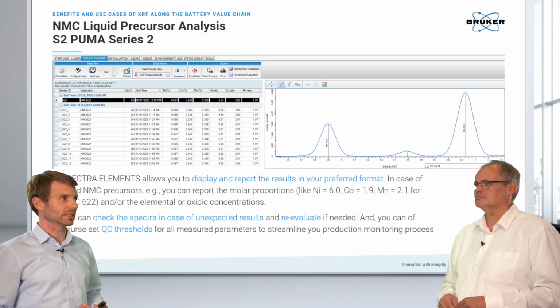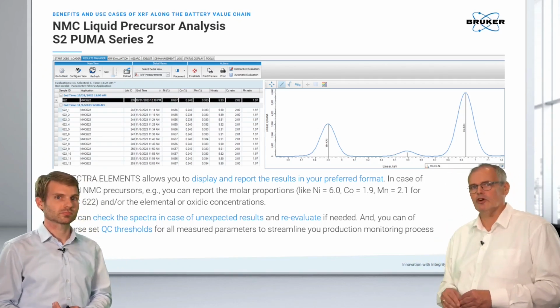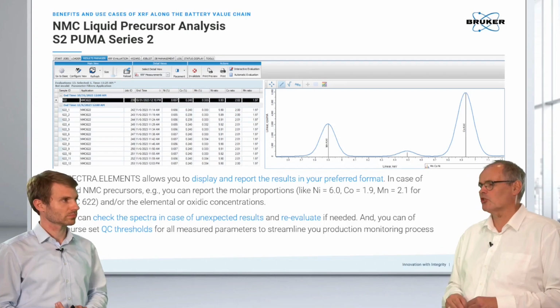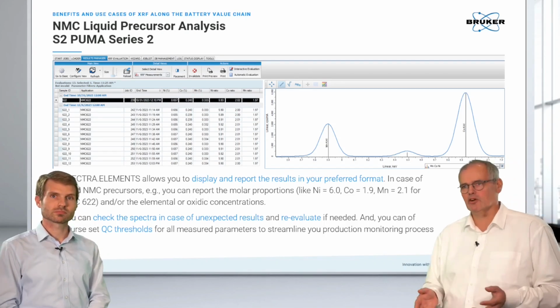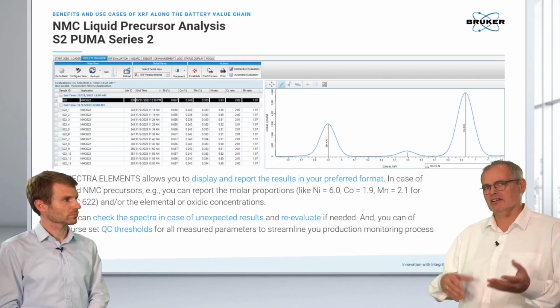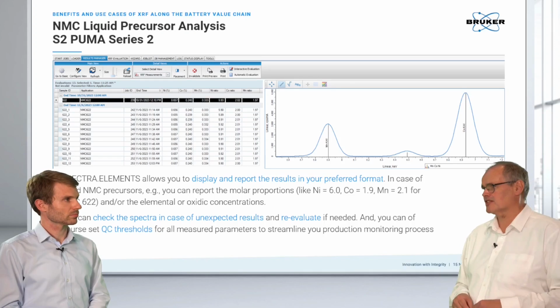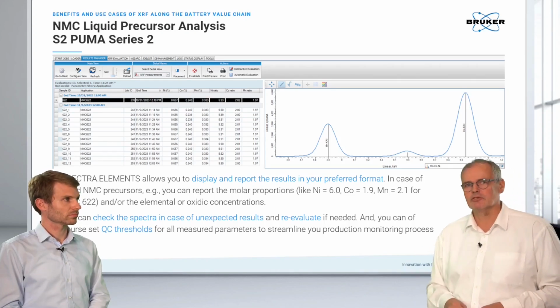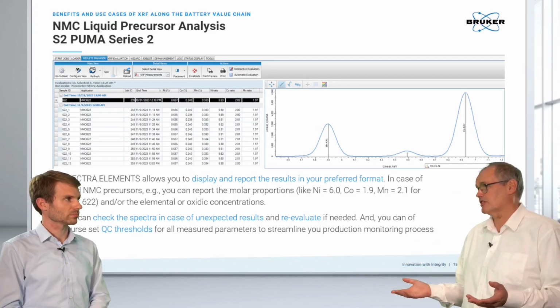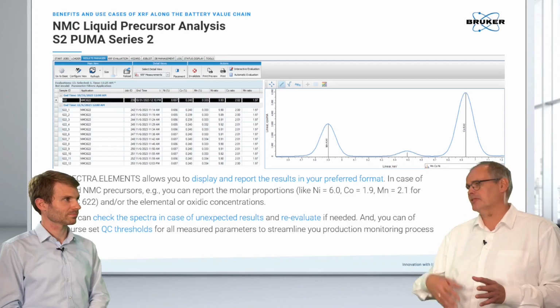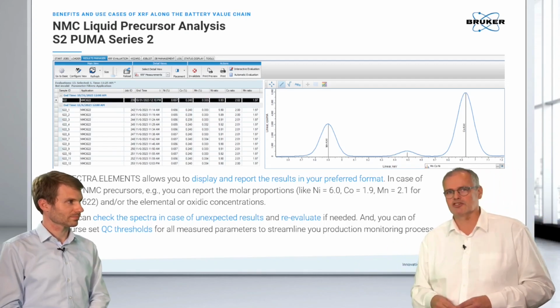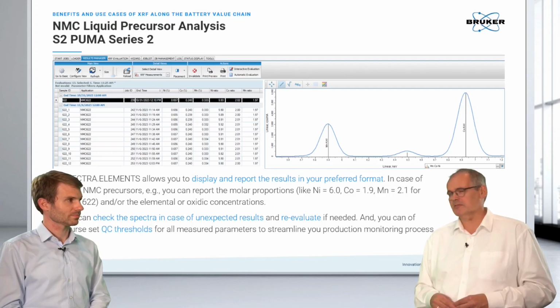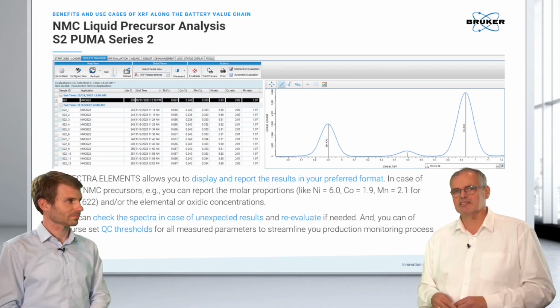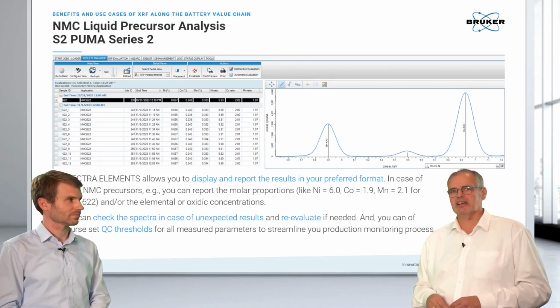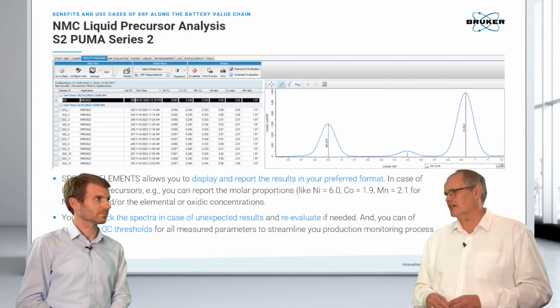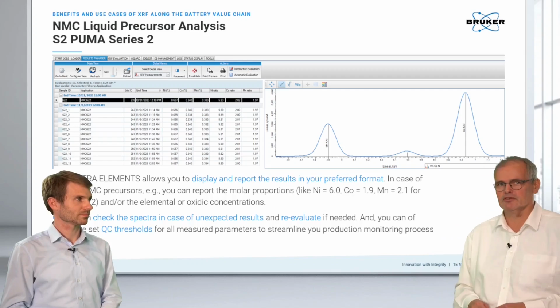The big advantage here we also wanted to point out: you see there is the spectrum shown, and whenever a sample is out of spec or you get a warranty claim that sample cells of a production batch might not perform as well, you are able to look at the spectrum and see if there is a contamination. Maybe the ratio is okay, but there might be a contamination which leads later on to performance issues. So you can evaluate all those spectra. They are stored in the instrument even after weeks. You can go back and see that this batch had a problem, and evaluate if this was the precursor material you have used.